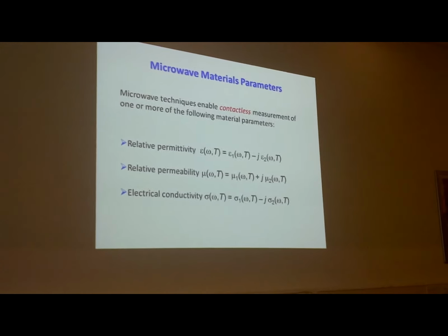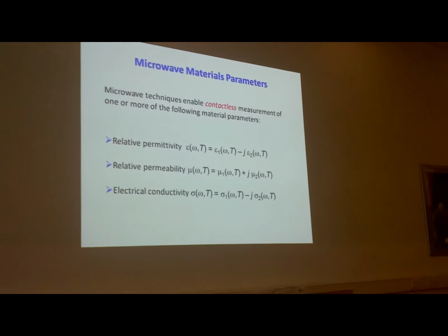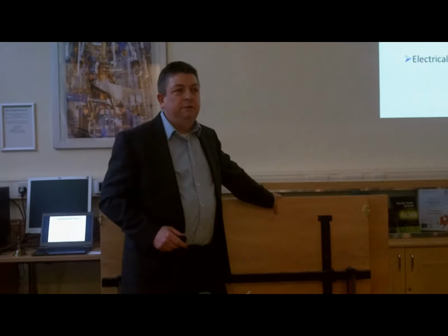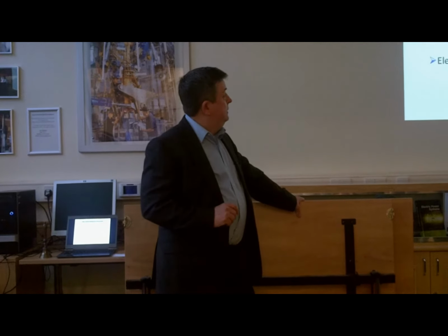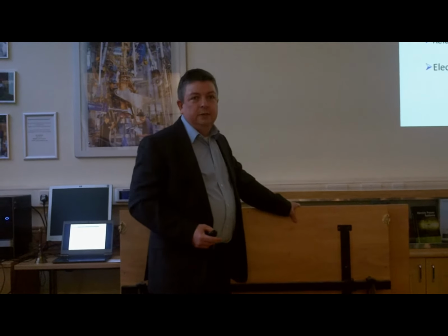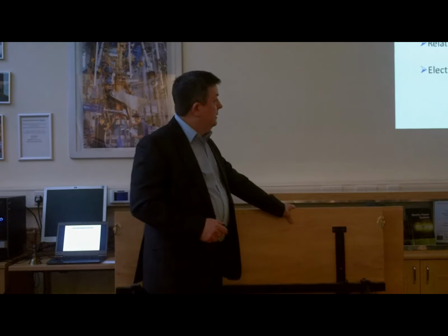And the sort of things that we measure, anything we can really, but the main constitutive parameters that enter into Maxwell's equations, of course, are things like permittivity and permeability, which quantify the electric and magnetic response of a material. But the nice thing about this is that we're doing it contactlessly. We're just putting something in a microwave field, seeing how that field interacts with the stuff, and hence then working out what the stuff is doing from that fundamental interaction.